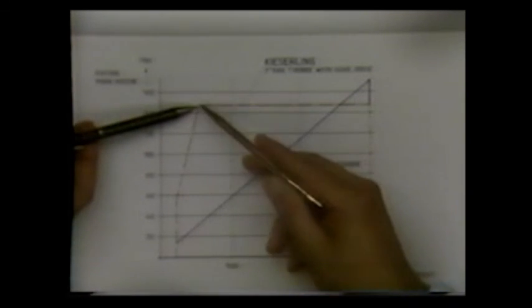The next figure shows these interrelationships in the form of the performance specification of the DC drive for a Kieserling 3-inch centerless bar turner with 150 horsepower. The hollow shaft has a variable speed control range of 1 to 50 with two gear steps and is field controlled after approximately 1/6 of the maximum speed, starting here with the field control. By way of comparison, the characteristics of a 170 horsepower drive without field control have been plotted.